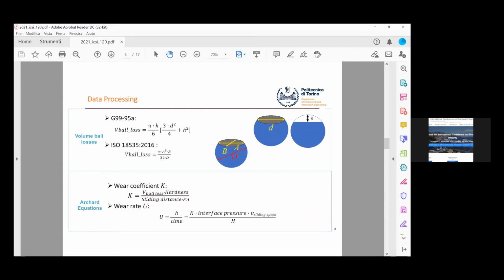Once the volume of the wear product, the sliding length, the normal force between the surfaces and the hardness are known, the wear coefficient can be calculated thanks to the Archard equation. And the wear equation can be also expressed as the wear rate.